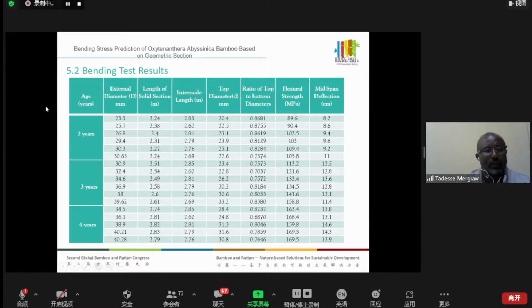The other testing, that's the main part of the research, is the bending test result. Here, as I mentioned earlier, the bamboo was categorized age-wise as 2, 3, and 4 year, and bottom diameter and solid section length, as previously stated, and the internode length and the top diameter are geometrically measured, and we have the ratio of the top end to bottom. Then the flexural strength and the mid-span deflection are measured. These results are outputs from the UTS machine.